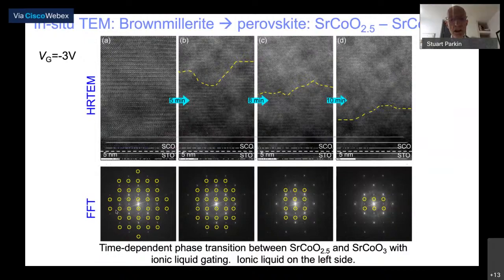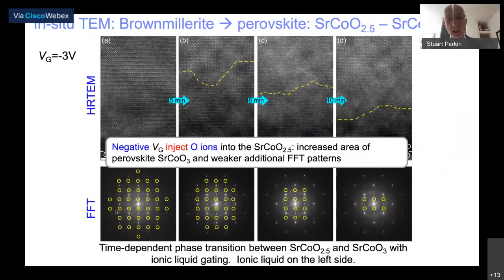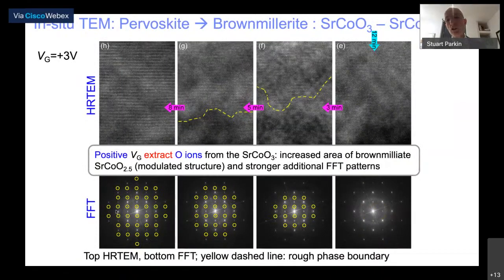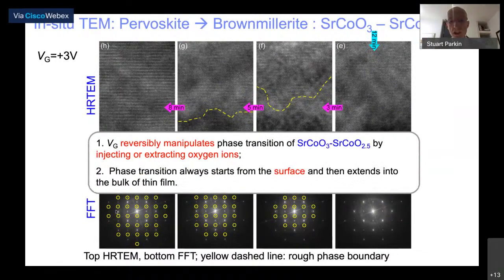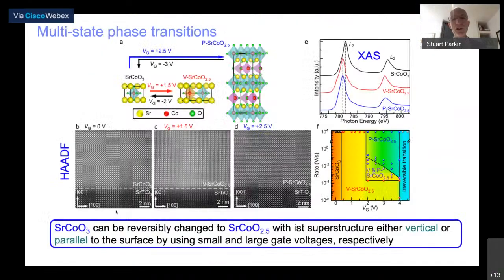In this case, we're injecting oxygen ions into SrCoO2.5 to go to SrCoO3. If we reverse the voltage, then we can go backwards and basically remove oxygen. So we can do both things. Why am I telling you all this? Because we want to use this idea to create spin textures.